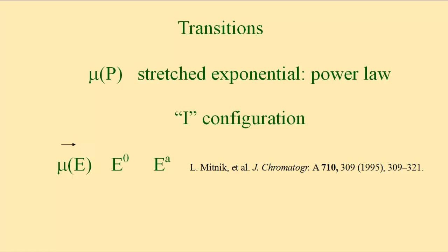Finally, for moving polymer chains, polyelectrolyte chains, the electrophoretic mobility can depend on electrical field. For weak fields, it doesn't. We're in the linear regime. However, as shown by Mitnik et al., if you run up the electric field enough, you get into a region where the apparent electrophoretic mobility depends on the strength of the electrical field as a power law. You have moved fairly conveniently and directly into a region in which nonlinear dynamics have become important.